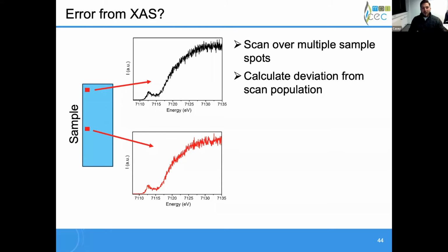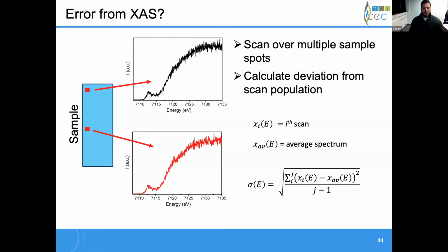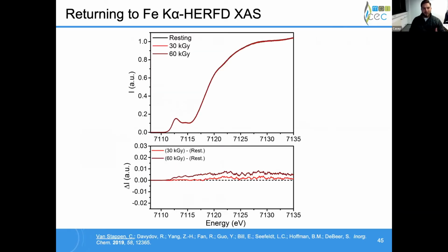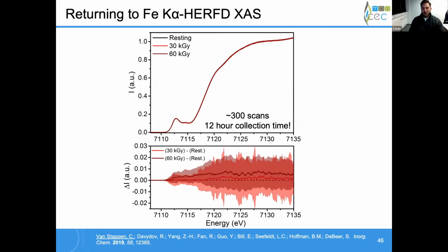Now, since we have a scan population though, that means that we can actually use the individual scans to go ahead and calculate our deviation. All we have to do is define χ_i as our ith scan, and then calculate the average spectrum. And from this, you can really easily get out the standard deviation of your spectrum. So if we take this definition and bring it back to our K alpha HERFD XAS, we find that none of these differences are even remotely significant.